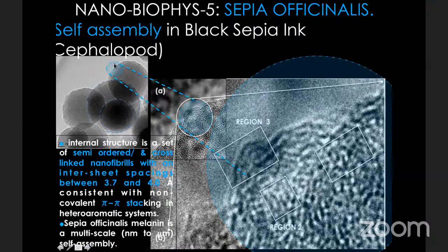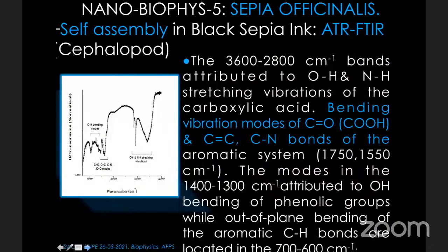And when you zoom more on these nanoparticles at the edge, in particular, when you go to high resolution, you will find out that in effect you have chains of DHICA forming semi-ordered or cross-linked nanofibrils with a lamellar sheet spacing between 3.7 to 4 angstroms, in line with the pi-pi stacking. A very well structured system related to self-assembly.